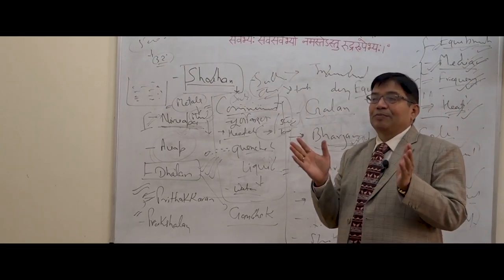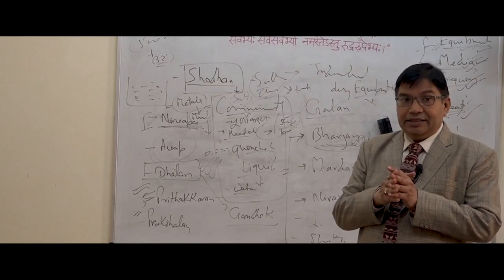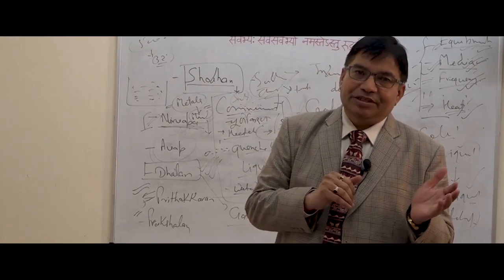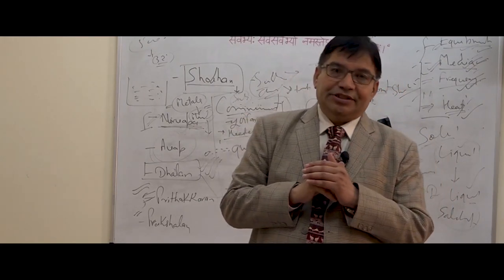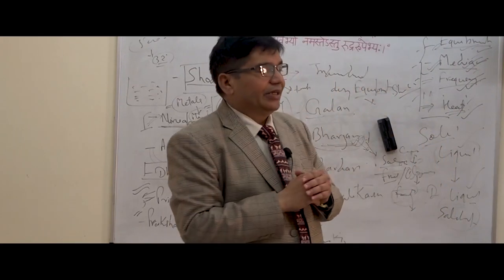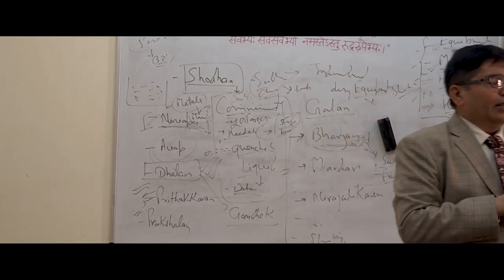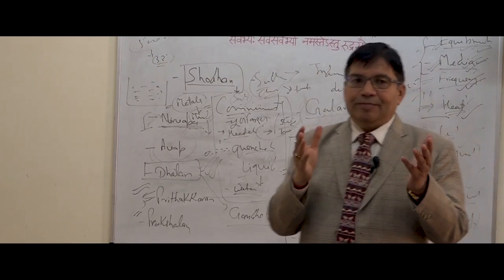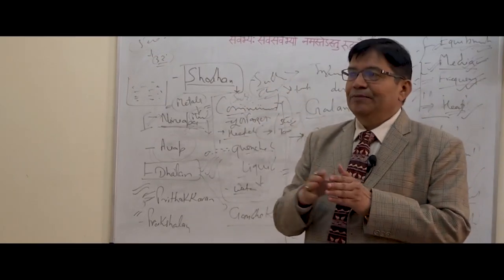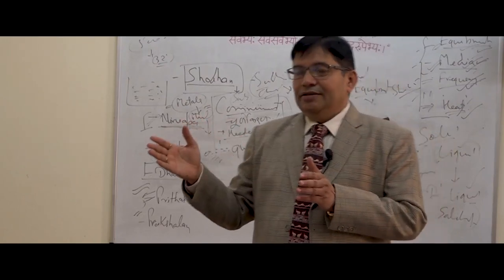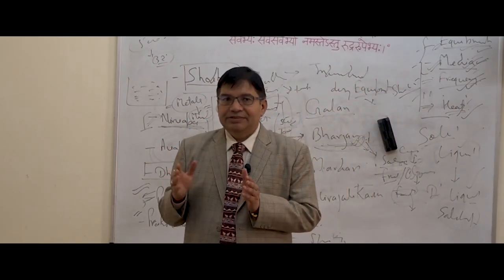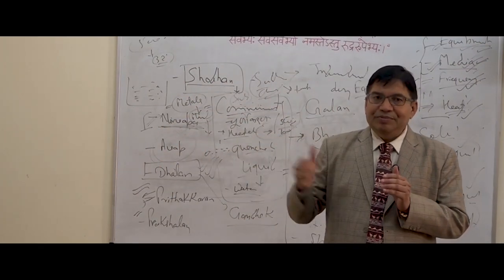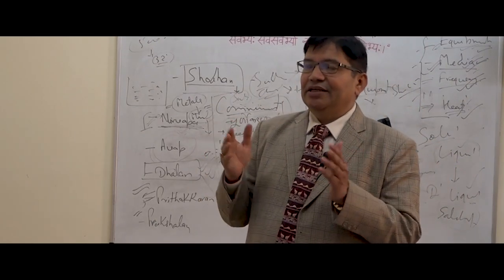One thing more, this Shodhan is not only for the reduction in the particle size. It is serving some more purposes also, and those purposes are the inculcation of the therapeutic properties in that particular metal or material, and the reduction in the toxicity. Here is a work that has been done at the PhD level, and Dr. Ved Prakash did it. He took the copper turnings and quenched them 35 times, following the method of the Shodhan, where it has been said that 7 times each will be quenched in 5 different liquid media having different pH and other properties.